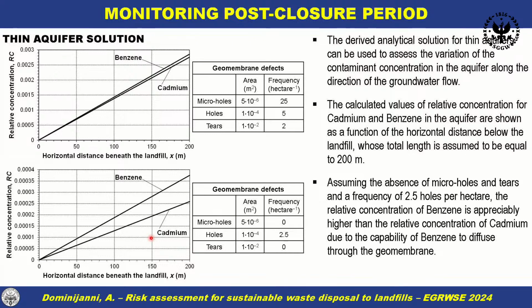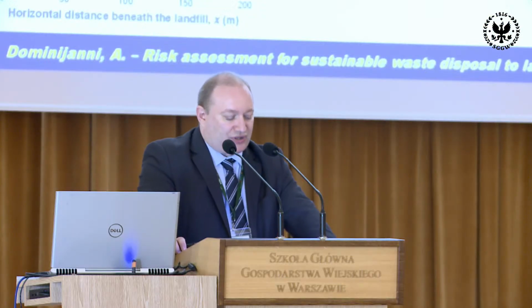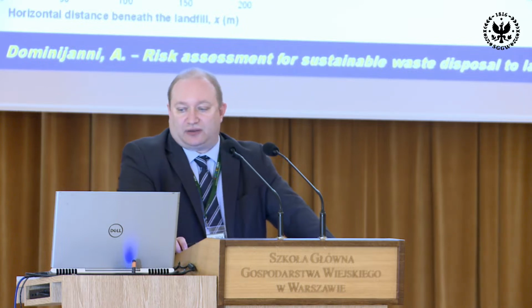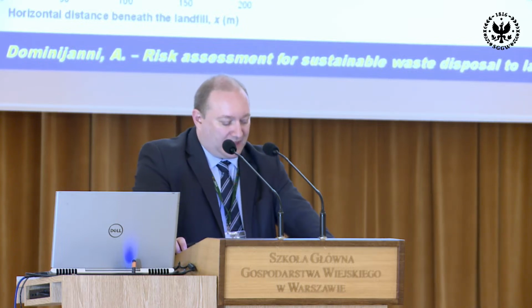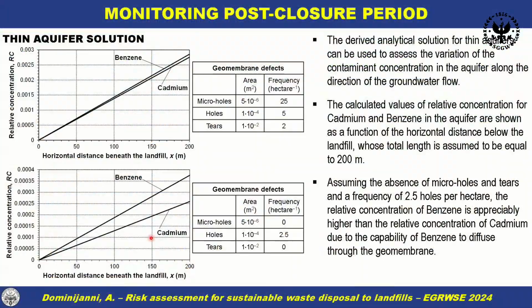The calculated values of relative concentration for cadmium and benzene in the aquifer are shown as a function of the horizontal distance below the landfill, whose total length is assumed to be equal to 200 meters. Assuming the presence of microholes, holes, and tears with the areas and frequencies shown in the table at the top of the slide, the concentration profiles for cadmium and benzene are similar.